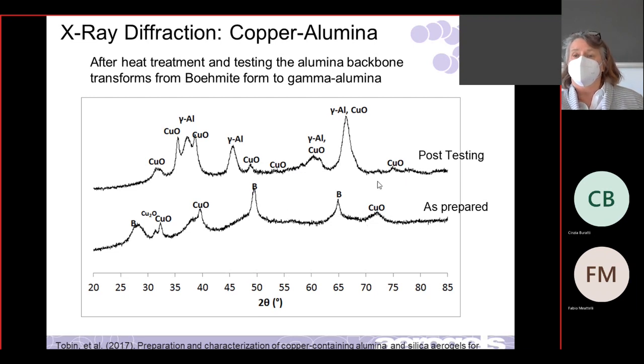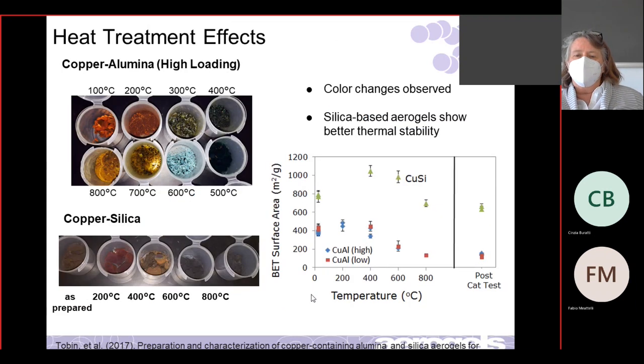And then we looked at heat treating these materials. So these are the different colors. So if we go like from a red to redder to kind of green. So this means that we put it in an oven. Left it in the oven for hours, and I don't recall exactly how many, at 100 degrees C, and took it out and looked at it. Did the same thing at 200 degrees C. These are all different samples, but they go through all of these, so 1, 2, 3, 4, 5, 6, 7, 800 degrees C. They go through these weird color changes as we do this.